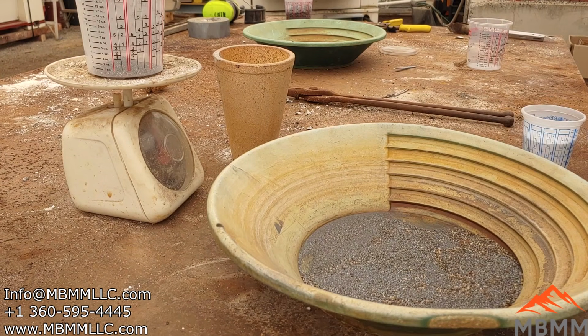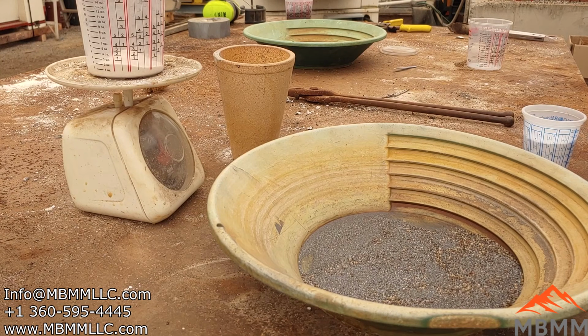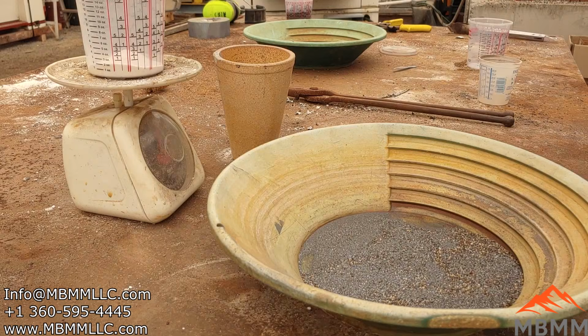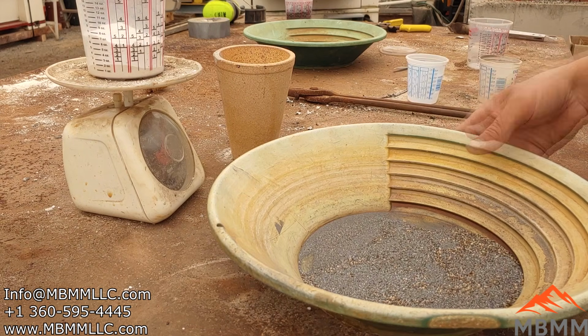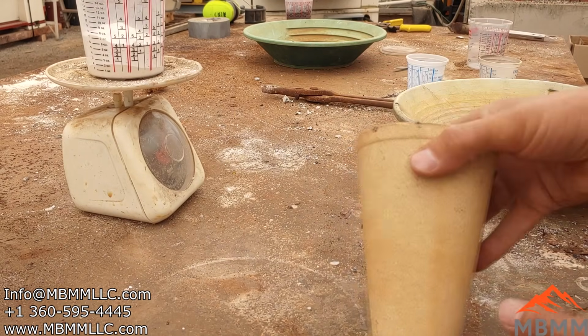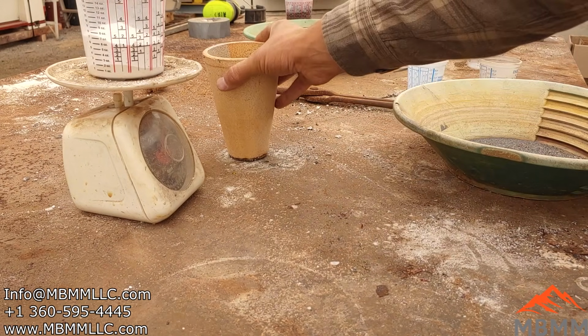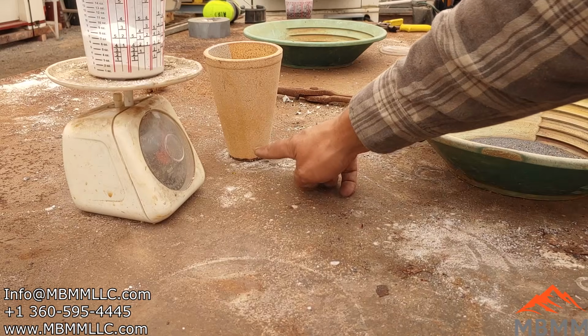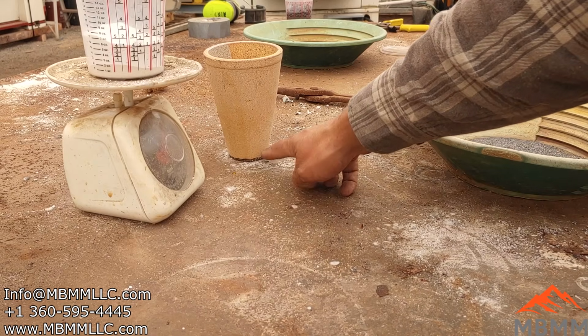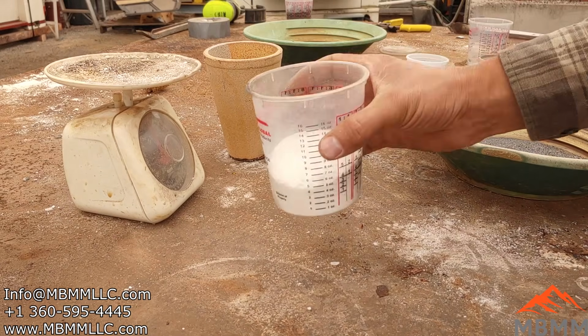The iron's going to take up the sulfur, turn it into iron sulfide. The lead sulfide will turn into lead metal. And the silver will follow the lead to the bottom of the crucible. We're going to use one like this. Down to the bottom of the crucible, the silver and the lead is going to collect down here in the bottom, and then we'll pour it into a cone mold.